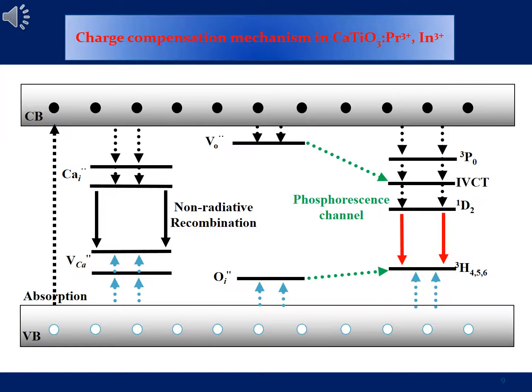Now, immediately there's going to be charge imbalance at a local site where I am incorporating praseodymium. And what will the material do? It will self-compensate by generating other point defects. Those will correspond to calcium, correspond to titanium, in order to balance this additional charge, which is positive. Now, if we generate calcium defects, we're generating defects which are not desirable, because all the electrons which are trapped there will de-excite non-radiatively. This is an effect we do not want. Now, what would I rather do in this case? What I would prefer is to compensate for this charge imbalance myself, instead of having the material compensate for itself.